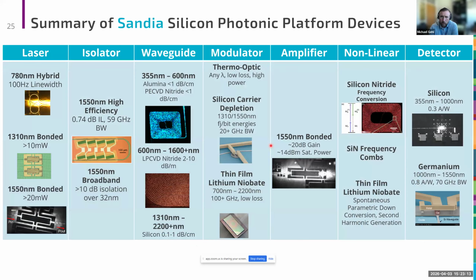And so to just kind of summarize, we've got a pretty wide range of devices that we've developed over the past 15 years or so. We're continually working to improve these, but just to give some examples, we've got integrated laser technology from near infrared out to telecom. We've got isolators that work at telecom with very low insertion loss and over very broad bandwidths. Our waveguides are functional from as low as 355 nanometer wavelength out to 2 microns with very low losses across that full range. We've got various different optical modulators. As I highlighted, we have thin film lithium niobate and lithium tantalate modulators, sort of your traditional silicon carrier depletion modulators, and then thermo, and I guess I forgot to mention it, thermo and piezo tuning of various devices.